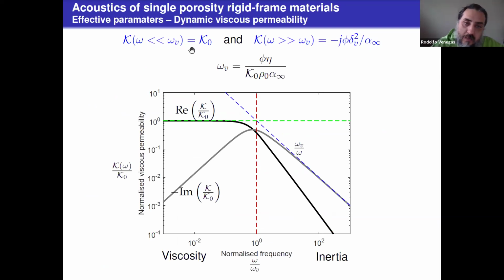Before that, let us recall some properties of the dynamic permeability. If we scale it with its static value, at low frequencies it will tend to 1, and in this regime the fluid flow is dominated by viscosity effects. As the frequency increases, we have a transition where the real part and the imaginary part have the same magnitude, and that happens at the Biot characteristic frequency, or viscous characteristic frequency. The imaginary part shows us how strong the dissipation of energy is, so it will be maximum around this frequency. Then when we keep increasing the frequency, this parameter becomes mostly determined by the imaginary part, with a dependence of 1 over omega.